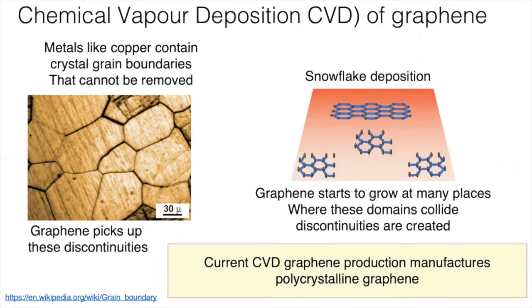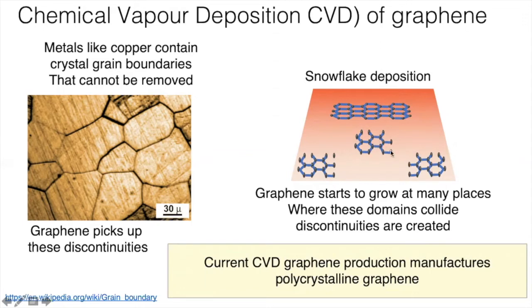There's something called the chemical vapor deposition or CVD route. We start off with a piece of blank copper foil or nickel, usually. The graphene can grow from several points — it's called snowflake deposition. It's a bit like the way snowflakes land on a pavement and gradually the surface is covered by a single sheet. The carbon lands on the surface and connects up in the lowest energy shape it can, which is the hexagonal chicken-wire shape that is graphene. But it starts growing from different points, called domains, and as the domains grow, they ultimately collide.